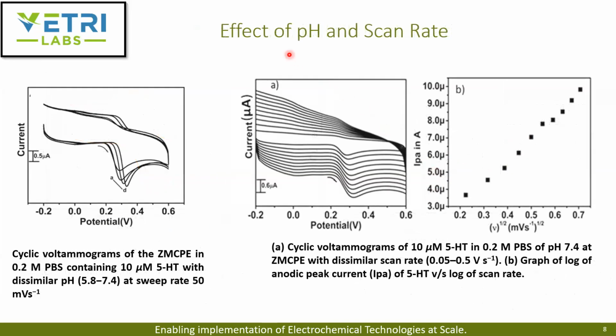To understand why, they did an effect of pH analysis on this setup. They changed the PBS buffer to alter the pH from 5.8 to 7.4. What they found was, as they increased the pH, the oxidation potential shifted more to the positive side, and there was also an increase in the current they were measuring. Since they got the maximum current at 7.4 pH, all their electrochemical studies were done at pH 7.4.